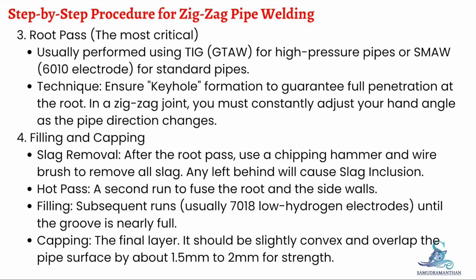Capping, the final layer. It should be slightly convex and overlap the pipe surface by about 1.5 mm to 2 mm for strength. Dealing with the zigzag angles.